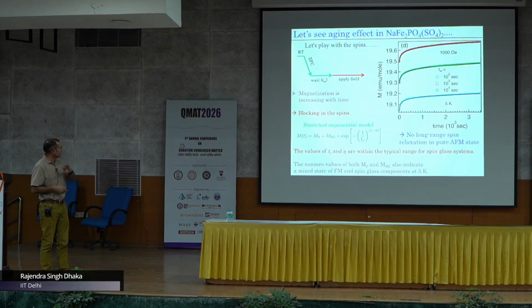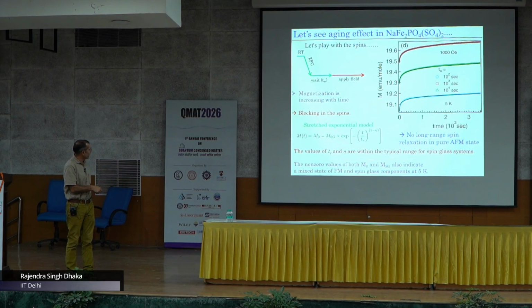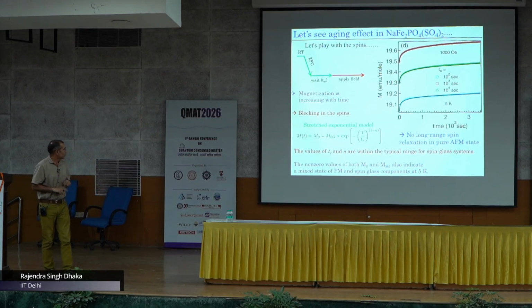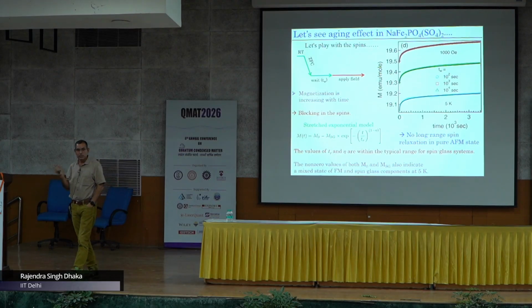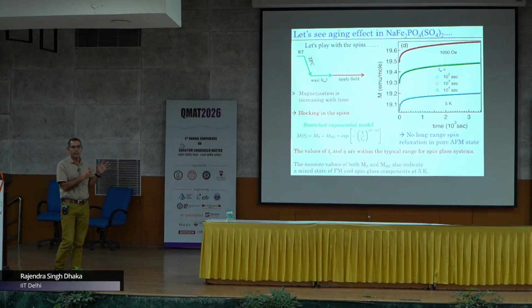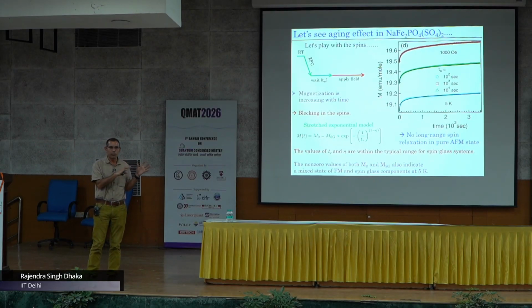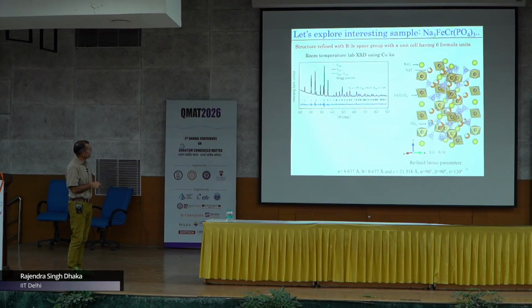Again this is, as I said, opposite. So, you use the same or similar exponential model, you have a minus sign here, earlier it was a plus sign. You do the fitting again and extract the parameters, and that will again give you the idea about the magnetic ordering. So, what we again found out from here is that these parameters are indicating that there is a spin glassy behavior in this system. So, concluding this study on this sample, we found that the antiferromagnetic ordering and the ferromagnetic ordering are competing with each other.